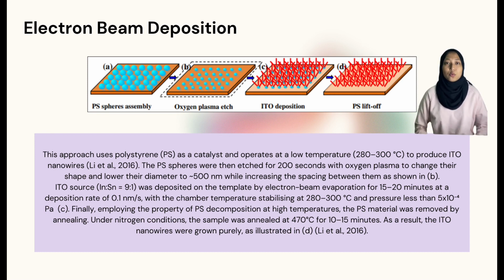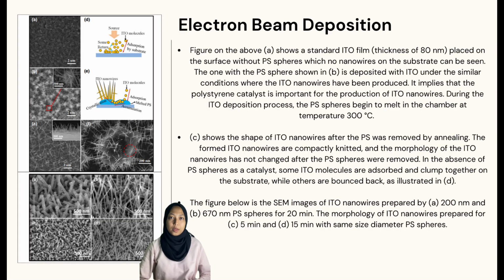Finally, the PS material was removed by annealing under nitrogen conditions. As a result, the ITO nanowires were grown purely, as illustrated in D. The figure above shows a standard ITO film deposited on the surface without PS spheres, where no nanowires on the substrate can be seen. The one with the PS spheres, shown in B, is deposited with ITO under similar conditions, and ITO nanowires have been produced. It implies that the polystyrene catalyst is important for the production of ITO nanowires.